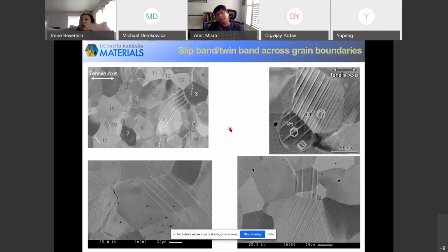So if you have another twin just like it, some distance from another twin, you have this anti-twinning stress field between them. And so studies of parallel twins have found that as parallel paired twins get closer to one another, the interaction stress between them is such that it enhances that anti-twinning stress. So it makes it even more difficult for twins to grow the closer they happen to nucleate.